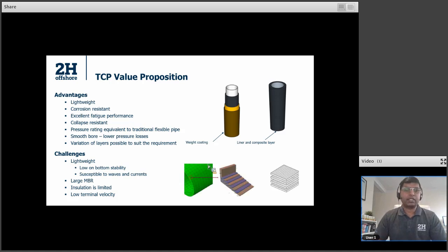We have large MBRs for TCPs compared to a traditional flexible pipe. That's because of the composite nature of the composite layer, where the alignment of different fibers within the polymer is quite critical. And if you apply any compressive strength, there's a chance that these fiber structures can dislocate themselves from the polymer structure and can cause integrity issues. And also because of the thickness of the structure, the composite layer has a higher stiffness compared to a normal polymer. So this results in a large MBR.